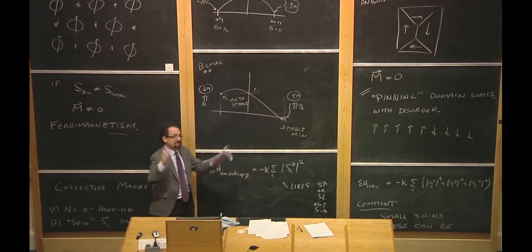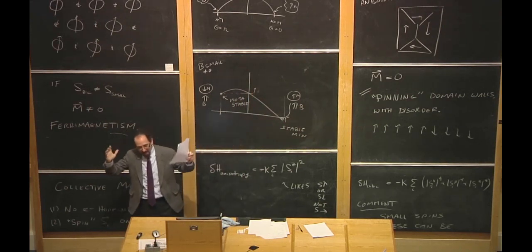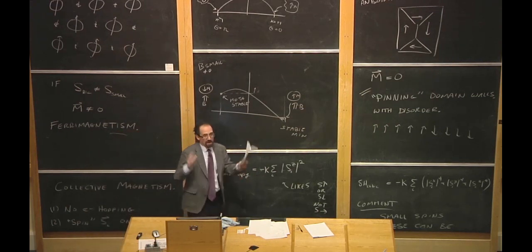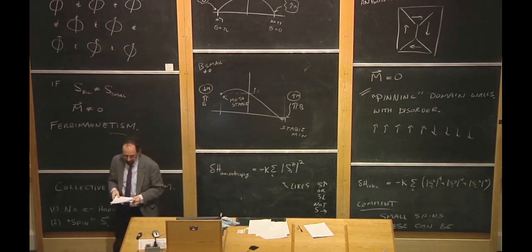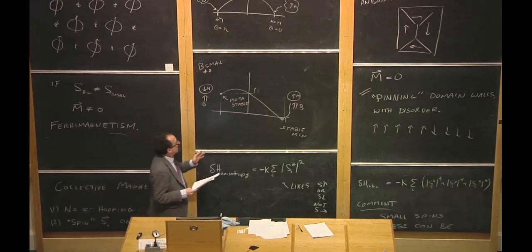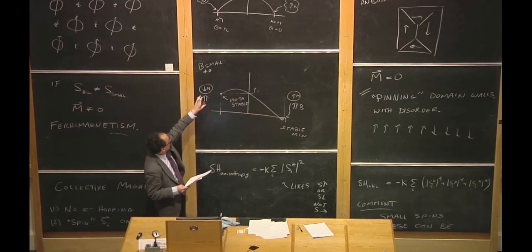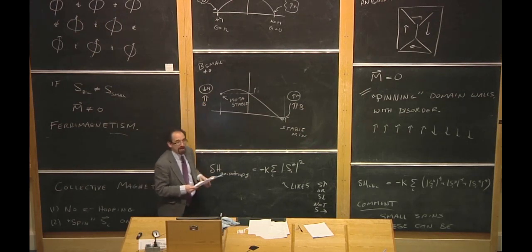And this means you have to take all of your atoms, maybe a million of these atoms, and somehow flip them all over simultaneously, either thermally or by quantum tunneling. And that's a process that's so difficult that at low temperature it may never happen. So you can have these little crystals of magnet have their magnetization stuck in the wrong direction.